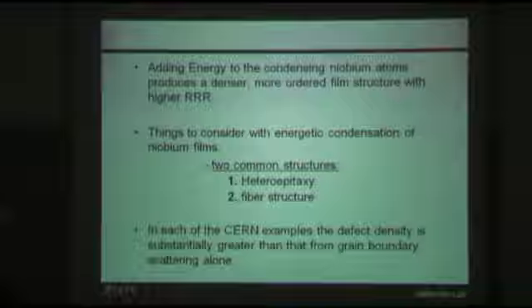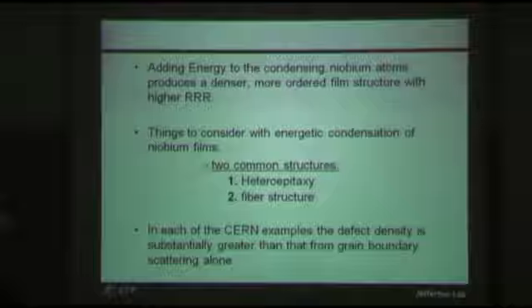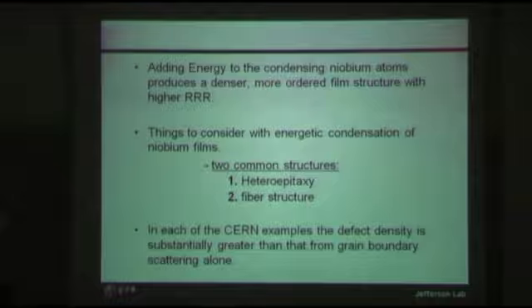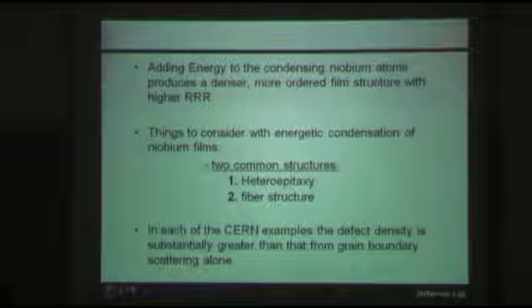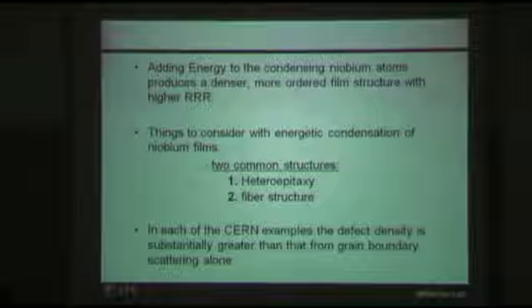It is interesting, though, if the grain size is of the order of 0.2 of a micron only, and the grain boundaries were completely opaque to electron transmission, which they are not, we would expect an RRR on the order of 100 if no other defects were present. So this is a potentially viable film structure. A value of 100 would have only a very slight impact on depressing HC1.